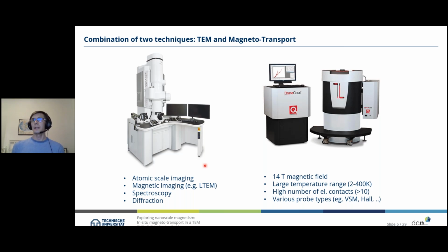And on the other hand side, we have dedicated devices to measure magnetic properties in a cryostat, where we can apply magnetic fields up to 14 Tesla. We have a very large temperature range going from 2 Kelvin up to 400 Kelvin, normally even higher if needed. It's quite easy to contact your samples with electrical contacts, which are normally more than 10. And of course, you have different types of probes which you can use, like a vibrating sample magnetometer. You have a Hall setup, etc.